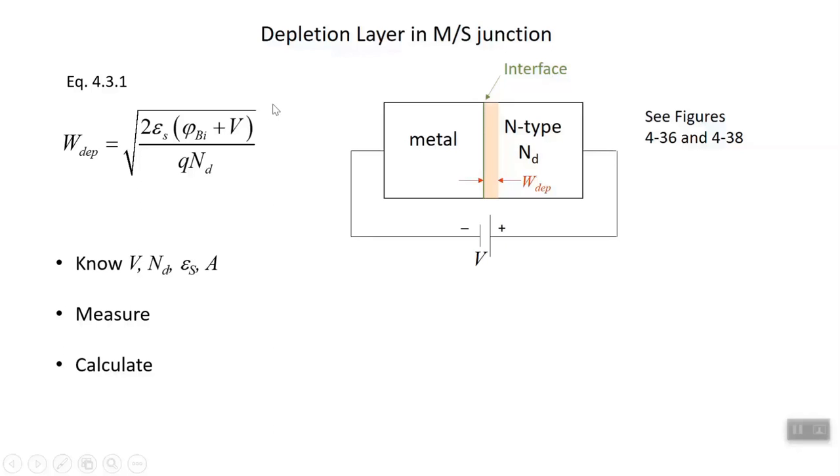That's going to require some measurement. What do we measure? You can't just take a multimeter and stick it across the diode and measure a built-in potential. How do you determine it? You determine it by measuring the capacitance of this junction, because capacitance has depletion width in it. This is the expression here. It's your standard epsilon A over D. That's what this is, a parallel plate capacitance expression, where A is the area of the junction, and the thickness is the depletion width.